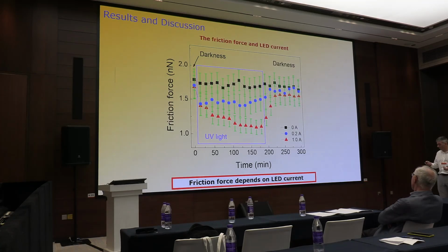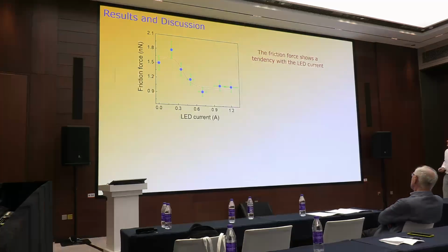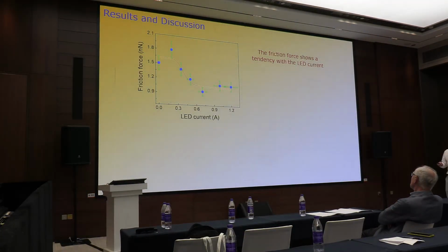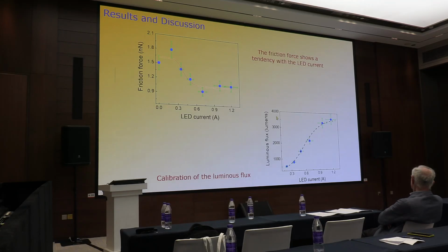Okay, the friction force depends on LED current. Let's go for one more experiment about the dependence on luminous flux. Here you can see the friction force as a function of the LED current. You can see that it starts here, then decreases and stabilizes here, saturating the system. This is a calibration. We could quantify the luminous flux in lumens as a function of the LED current. You increase the LED current and increase the luminous flux, and you can also see that there is a saturation of the luminous flux signal.